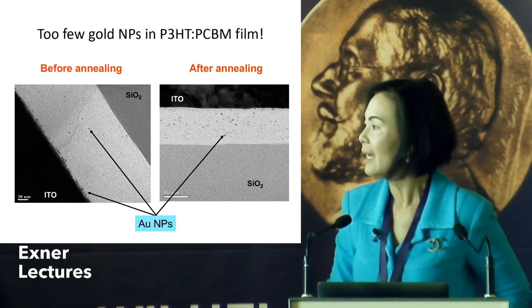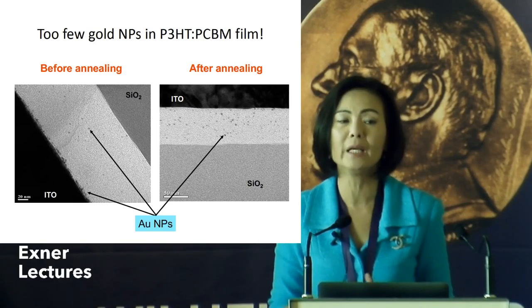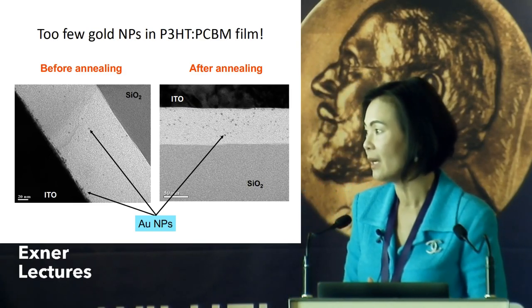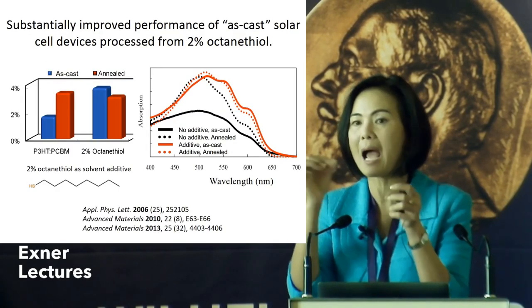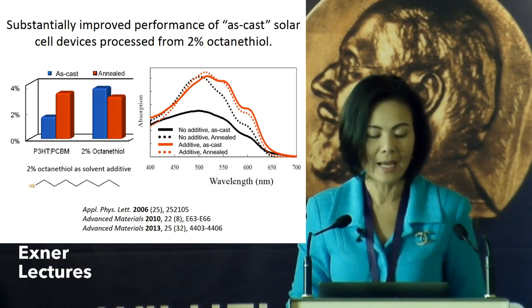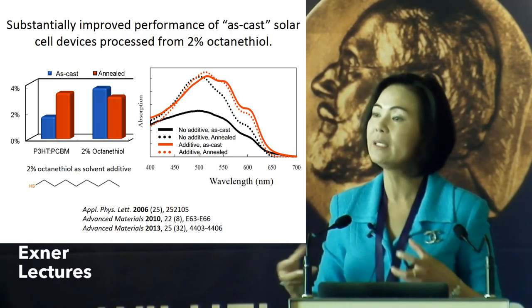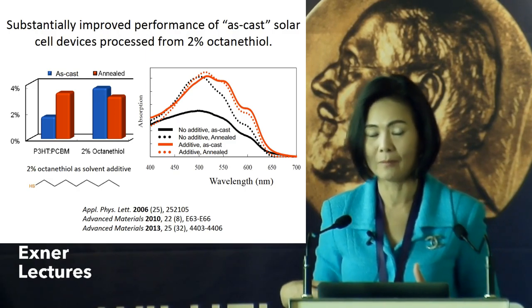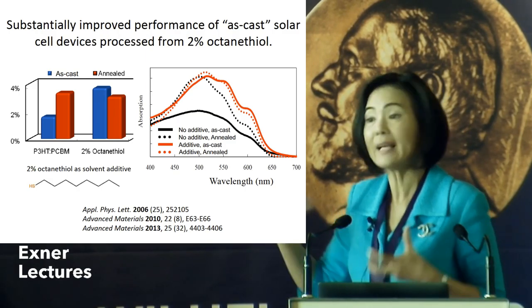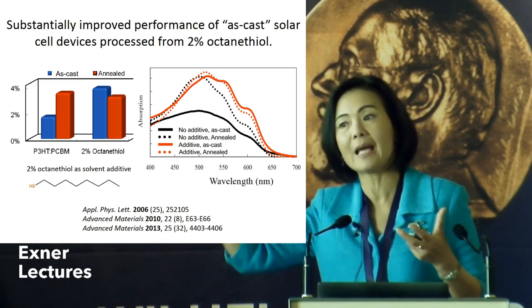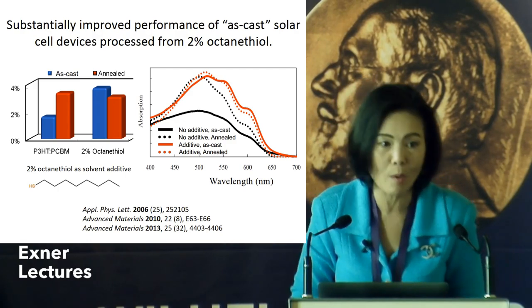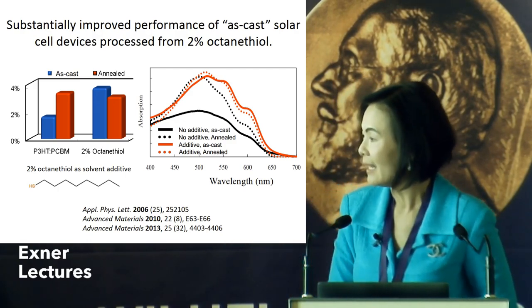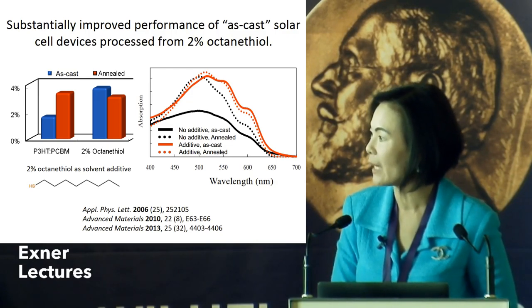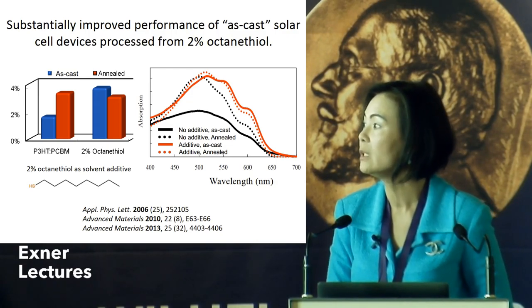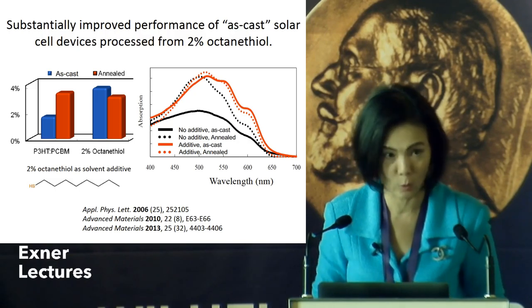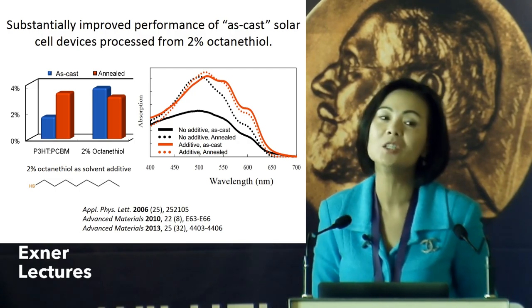device performance. And so we talked for 3 hours, meeting with the synthesis person, and asked him in detail how he made the gold nanoparticles. And then we found out that basically he used the ligand octanethiol. And the next easy control experiment was to add in the ligand without the gold nanoparticles. And so that's what we did. And so you can see here, we ended up having a really, really good performance with the ligand alone. And so that's how we discovered the additive.